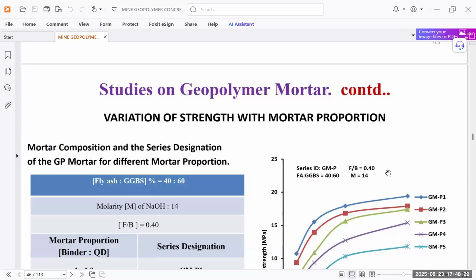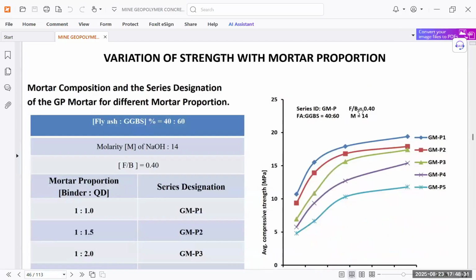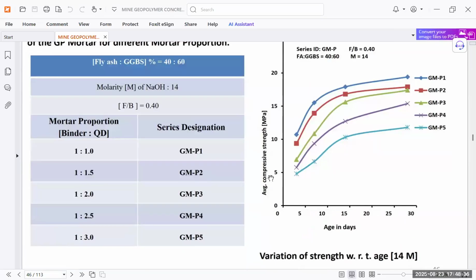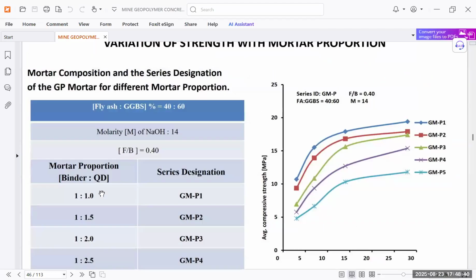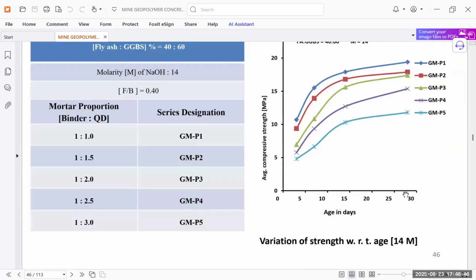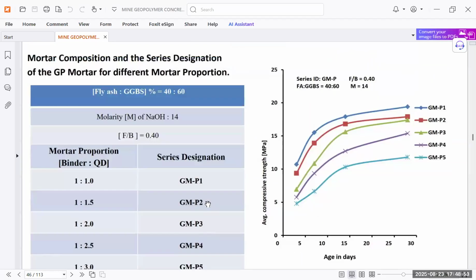Here the molarity is fixed and the fluid to binder ratio is 0.4. So that is why our average compressive strength is seen by different variation of this binder to fluid ratio we have taken. In this case, we have plotted this and different strengths we have obtained for different ages. So this way we can see that by using some different compositions, we can get results similar to RCC concrete, meaning concrete results, also by varying this molarity and varying this binder to fluid ratio.